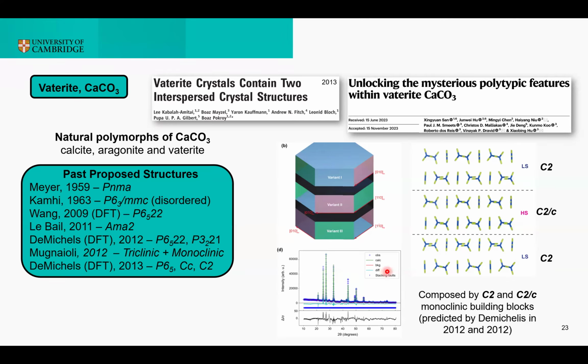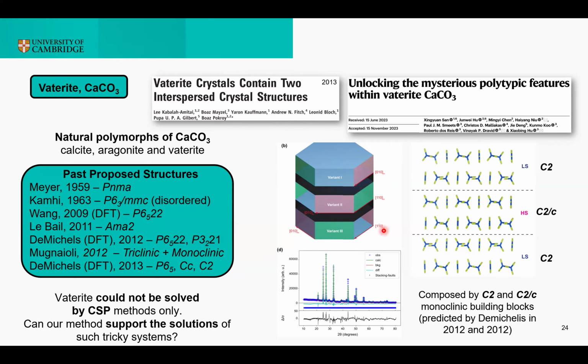Moreover, this work showed that two different monoclinic space groups could actually form this polytypic structure and explain the experimental observation, which were more or less favored thermodynamically depending on the temperature conditions. So, the successful solution of vaterite has required the combination of so many different analytical methods.